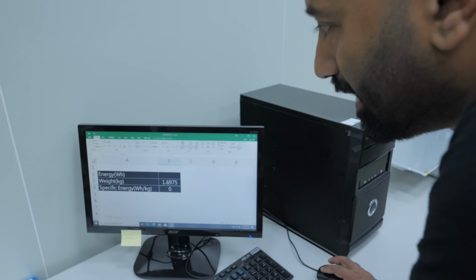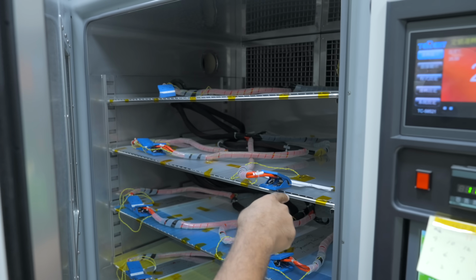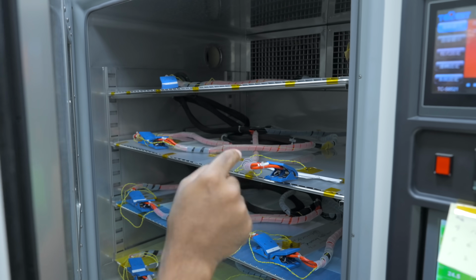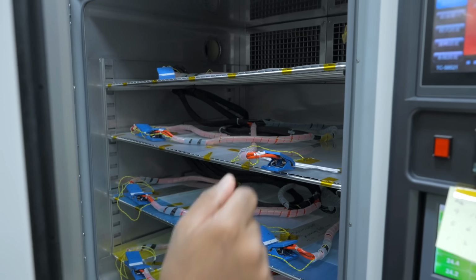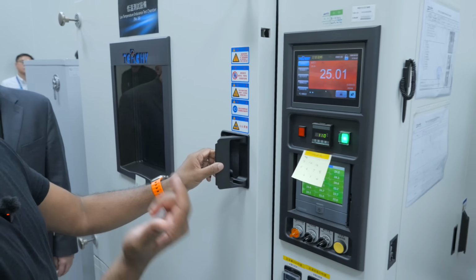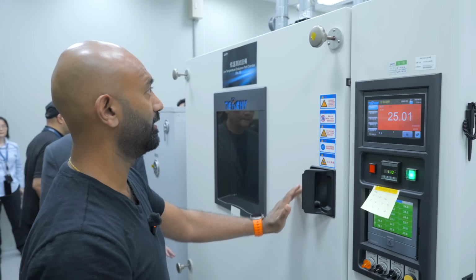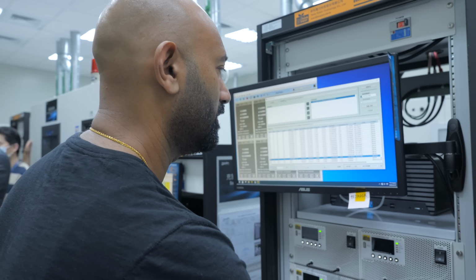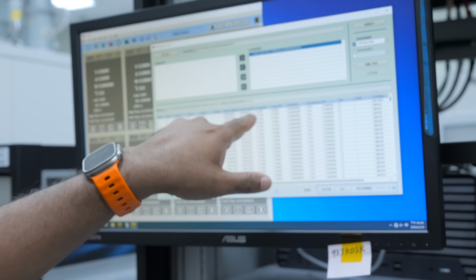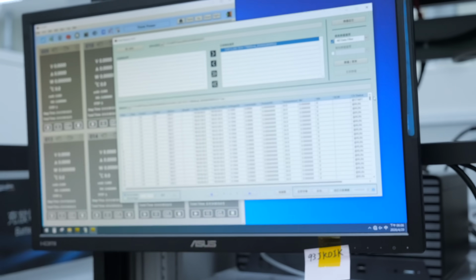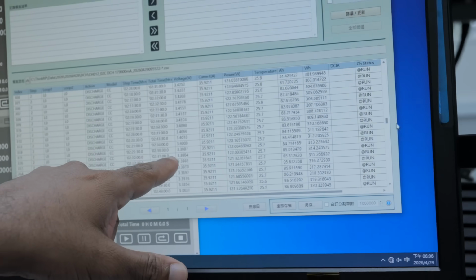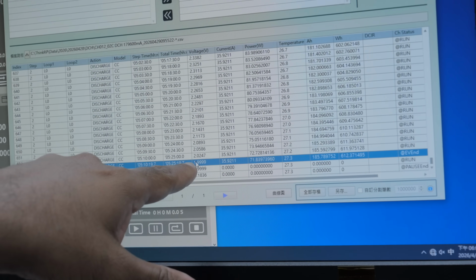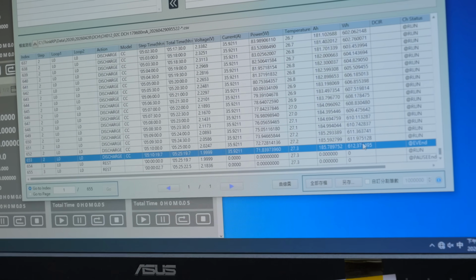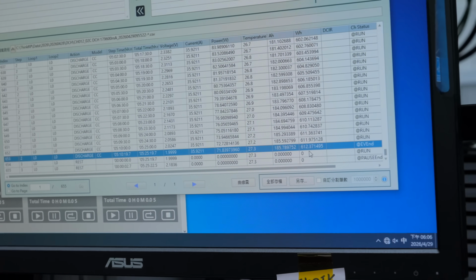1.6975 kilograms. Okay, so they're doing the energy density test to see just how much energy they can put in and get back out of these cells. So we'll go look at the monitor and see how they fare. We started with a cell here with a voltage starting at 4.1 volts and ran the test until the voltage dropped to about 2 volts, and we got out 612.37 watt hours.